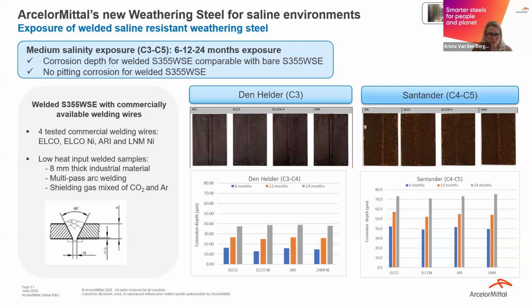In the welded state, we did an outdoor exposure up to 2 years in C3, C4 and C5 classification. And we did it with different types of weld. So we did 4 types of welding with commercial welding wire, and we evaluated the corrosion behavior. What we have seen is that for all these 4 types of welds, we have a similar behavior as our bare weathering steel. So it means that by having a weld on the material, we don't have localized corrosion, or a higher corrosion rate than the bare material without the weld. And this can be seen in these 2 exposure sites.